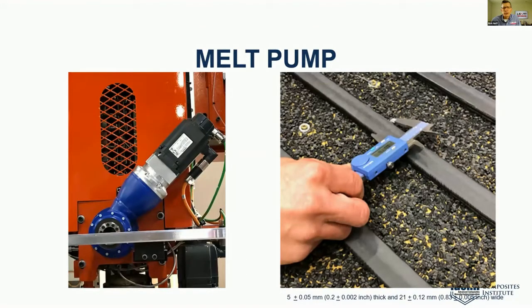Another unique feature is that the THERMWOOD system has something called a melt pump. And what the melt pump does is it exactly meters out the right amount of material so that you wind up getting a bead that's very accurate. The bead happens to be 5 millimeters tall and 21 millimeters wide, and it varies by very little, so that when you're creating a tool, you can exactly fill it up. You can make it with almost no voids in it.